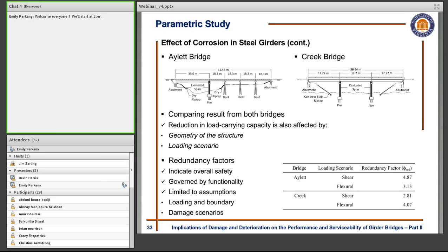And at the end, we defined the redundancy factor for both of these systems for shear loading and flexural loading scenarios. And as you can see in this table, all of these values are larger than 1. So it means that these selected structures under the selected range of damage are safe to operate. But if in any case you receive values lower than 1, we need to stop the operation of that specific structure. We need to perform an appropriate maintenance program and check these redundancy factors again to see if we get a value higher than 1, and at that time the structure is ready to get back to service.